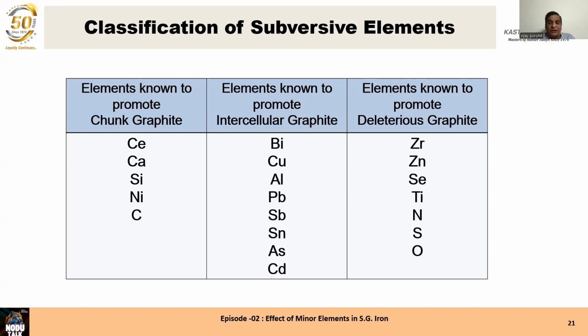So making heavy sections, keep this tip in mind. Use 50% ferrosilicon magnesium with rare earths and 50% ferrosilicon magnesium without rare earths, for cerium to react with these bad elements, as well as to avoid formation of chunky graphite if cerium is present in excess of 0.025.